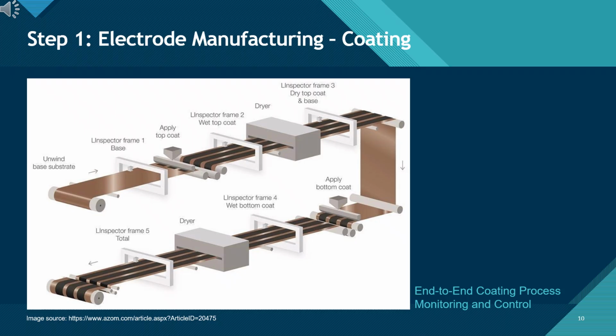Immediately after coating, the foil passes through a dryer to remove solvent and stabilize the layer. Next, the foil is flipped, and the bottom coat is applied, followed by another drying step. By the end of the line, both sides of the foil are evenly coated and dried, ready for calendering. What makes this system powerful is the inline inspection frames you see marked along the process.